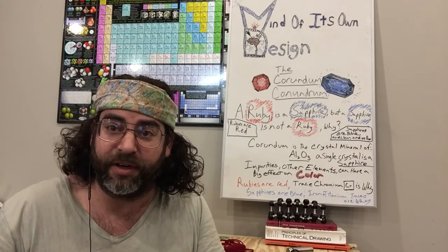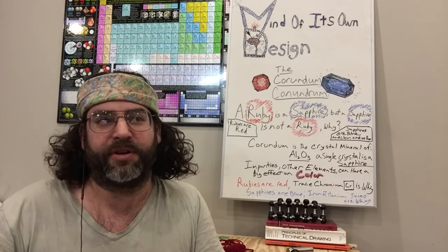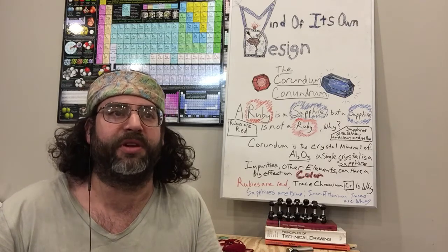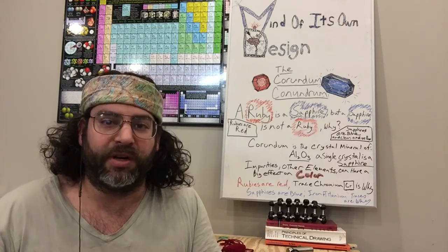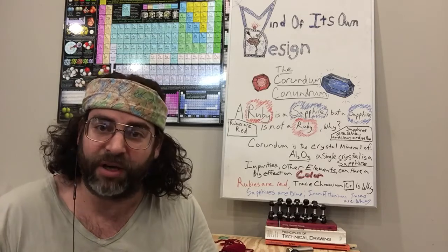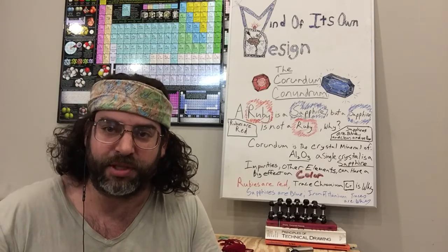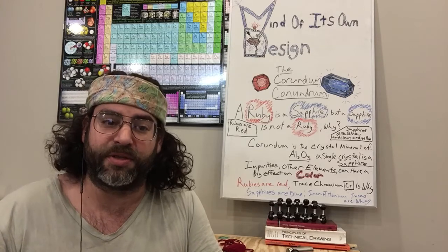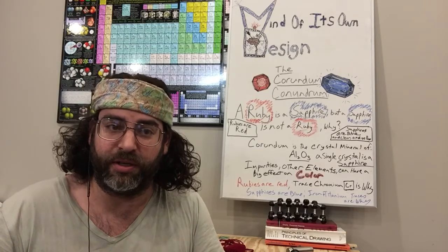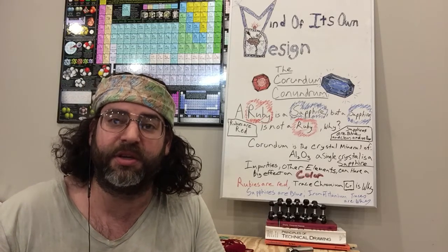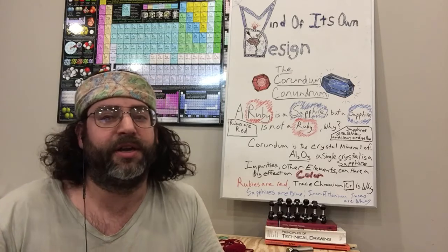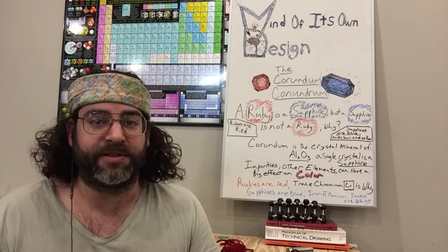And if you have a single crystal of that material, that is what's called a sapphire. So the sapphire is really pertaining to it being a single crystal. Whereas aluminum oxide could come in a polycrystal, which is white, or a single crystal without any dopant or impurities, which would make it clear. And if you have chromium, that makes it red.